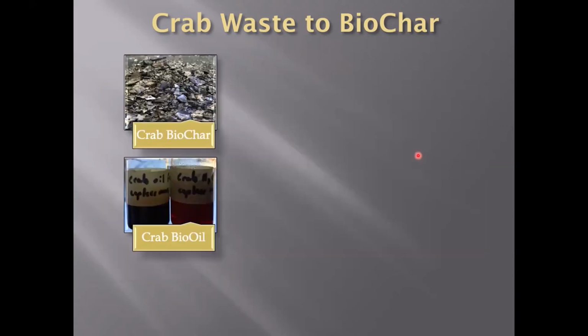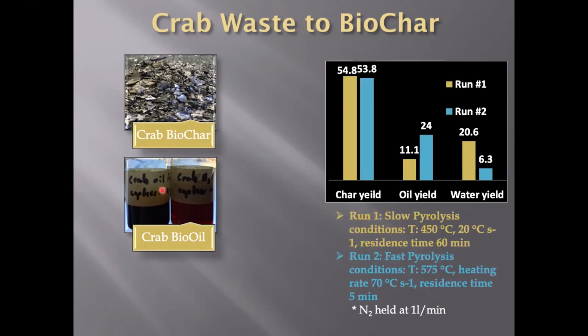Our main focus has been on the two major products of pyrolysis, which is the crab biochar and applications around this, as well as we've done a little bit of work on the crab bio-oil that's produced. So as I mentioned, we're able to run both fast and slow pyrolysis. The difference is that a slow pyrolysis unit generally heats at lower temperatures with slower temperature ramps for longer periods of time, where a faster pyrolysis unit will heat to higher temperatures with faster ramps for shorter periods of time, both under inert atmospheres. What you can see is that the yield of the char is generally the same, no matter which conditions we use.